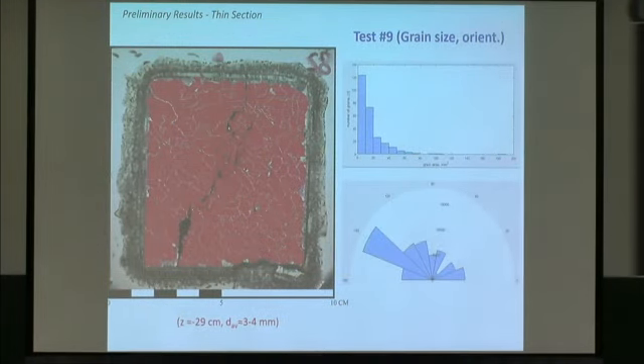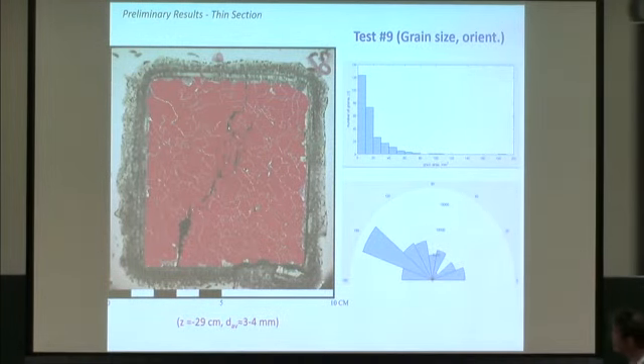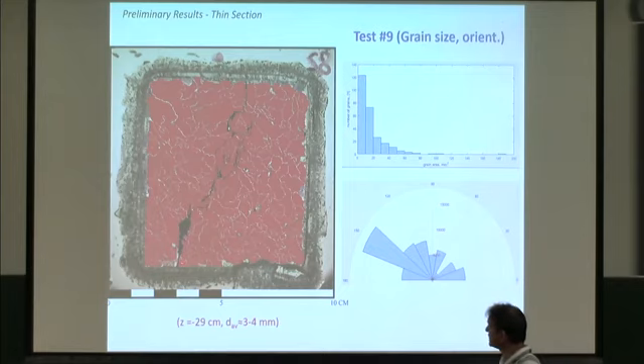If I go into this one, you can more clearly see the grains here. I haven't had time to calculate properly, but we are in the range of 3 to 4 millimeter average size of the grains. There's some statistics here. This is not diameter, this is grain area which is used. And then we do of course have also information on the orientation here.